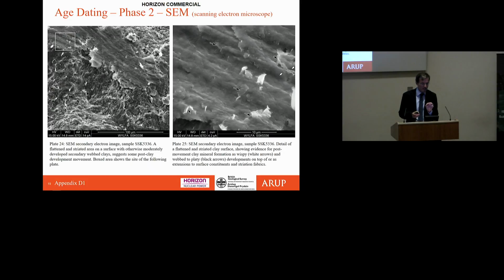But what you can see is there are these white clay particles that are growing on the surface. Okay, so now you've got striations, and over the top of those, clay particles have grown. So they've grown in situ on top of the striated surface. Okay, so now this is very key because that's bracketing our age. They've grown since the striations. Okay, that's very important. So we've now got something that brackets the age. But they're a couple of microns across, which means it's quite difficult to investigate further.